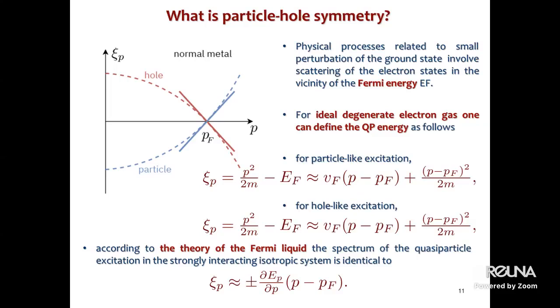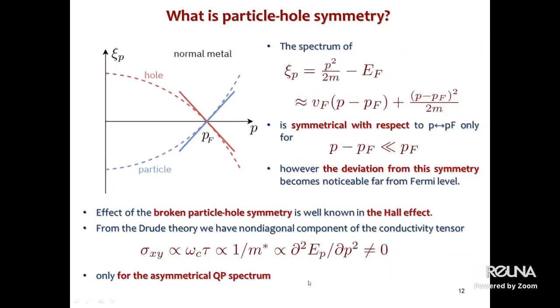For ideal degenerate electron gas, one can define quasi-particle energy as shown here for the particles and for the holes. Standard expression. Note that according to the theory of the Fermi liquid, the spectrum of quasi-particle excitation in the strongly interacting isotropic system is identical to that of the ideal electron gas, with the following expansion. So quasi-particle energy is a standard expression, with plus for electrons and minus for holes. Okay. Let's look at this expression. The quasi-particle spectrum is symmetrical with respect to interchange between P and PF, if we neglect this term.